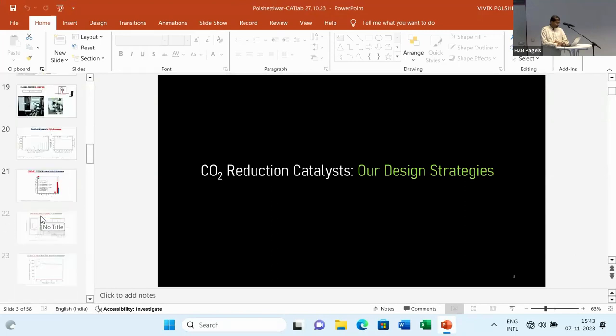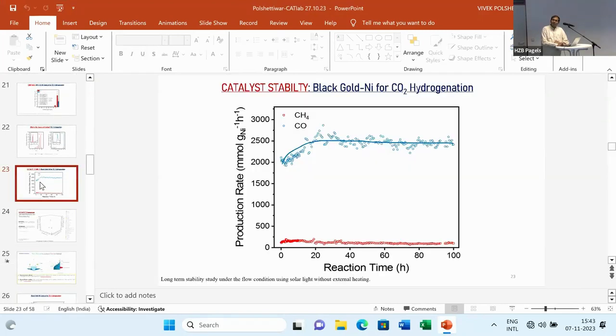Exactly, we faced that. I showed you this data. See, its activity is less and then it increases. This indicates that when we loaded the reactor, which we did in an open air environment, gold is stable. Nothing happens to gold in general for a short time, but nickel does go to oxide. So that's why you see this. And then after several hours, that nickel reduces to nickel zero and you get a good activity. So we characterized the catalyst here, and then we characterized the catalyst here. This is the in situ reduction of nickel then. This is in situ, yeah. Okay. So that's what we did with in situ reduction.